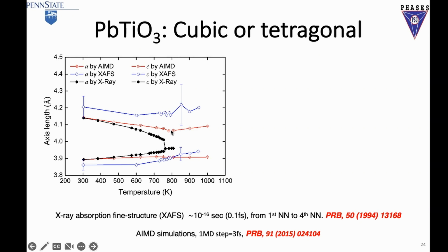But if the temperature goes up, you will see that the two lines diverge. And then this one maintains almost the same, doesn't change. A very nice agreement with experiment. So this simulation is purely DFT with molecular dynamics, okay, without any fitting there.